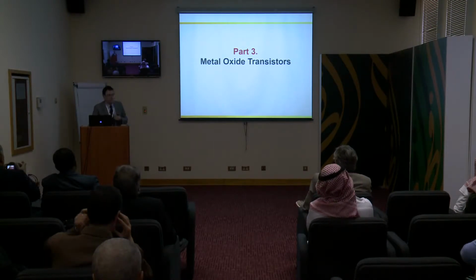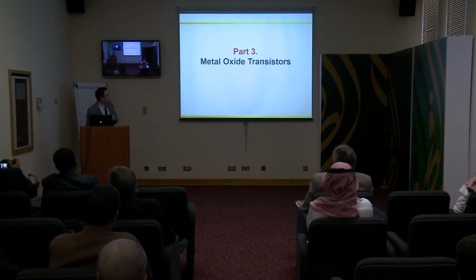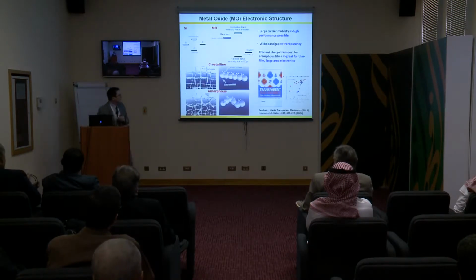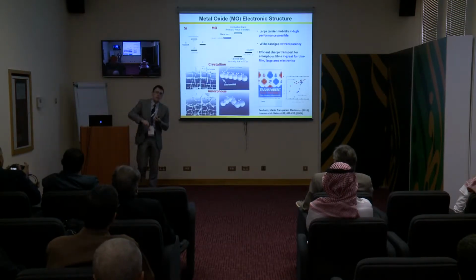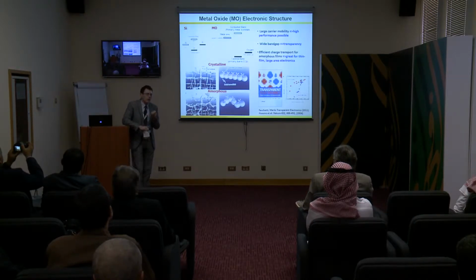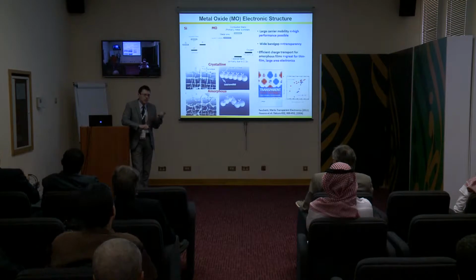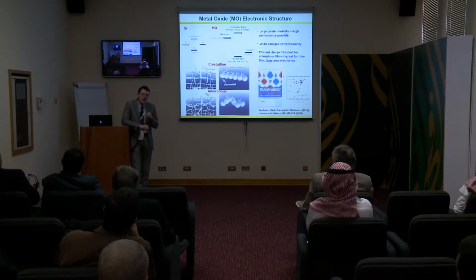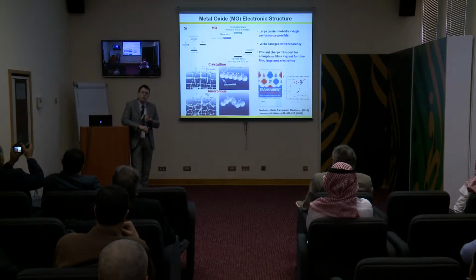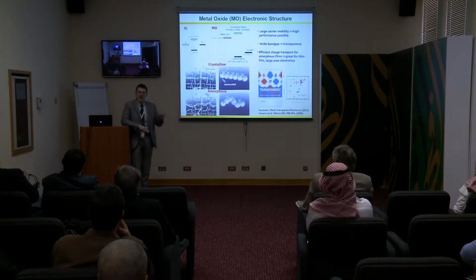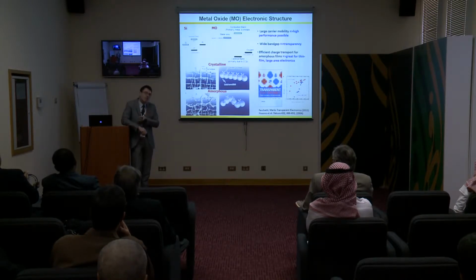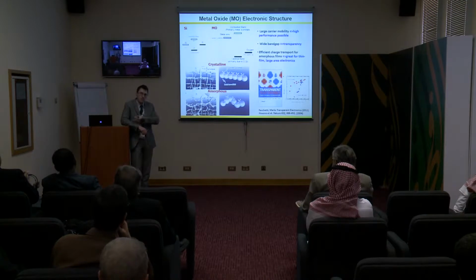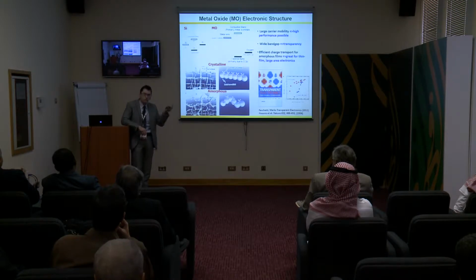So let me switch to another class of materials. They're still in the vision of printed electronics, which are the metal oxides. And metal oxides are a sort of competitor to organics, and the reason is because metal oxides, compared to silicon type of semiconductors, can exhibit very high charge carrier mobility also for amorphous phases. So for silicon, you have to have crystalline phases to get very high carrier mobility. When you go to amorphous silicon, the mobility drops 3 orders of magnitude. But for metal oxides, the difference in mobility between single crystal and amorphous phases is a few factors. A factor of 1, a factor of 2, very, very little.